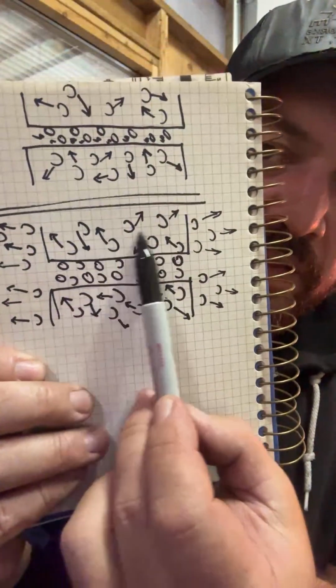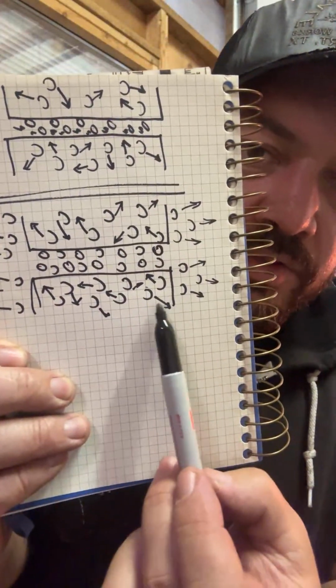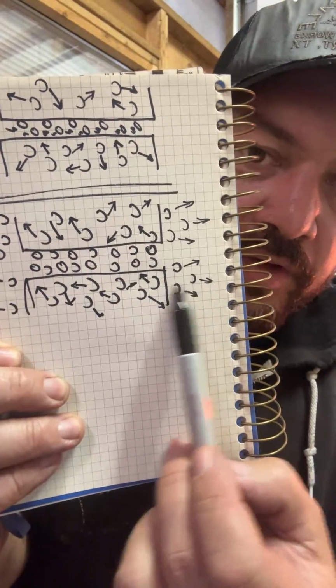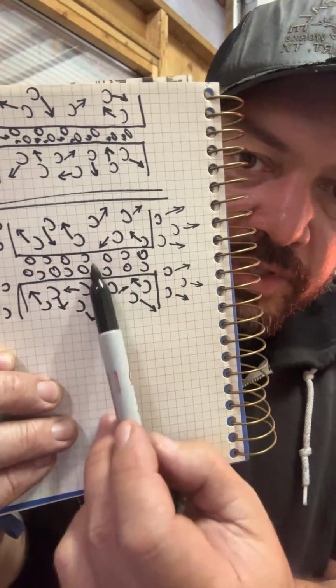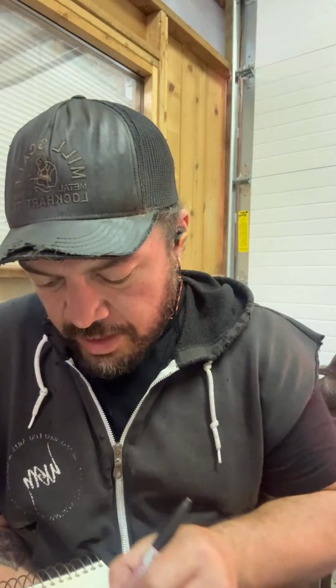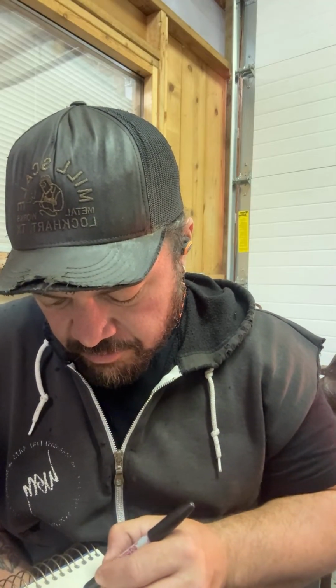Carbon moving around within the steel is also starting to off gas, not only from the edges, but also between these layers. So it gets to a point where it creates a positive pressure between those layers, and then all that's in there, carbon making its way out.